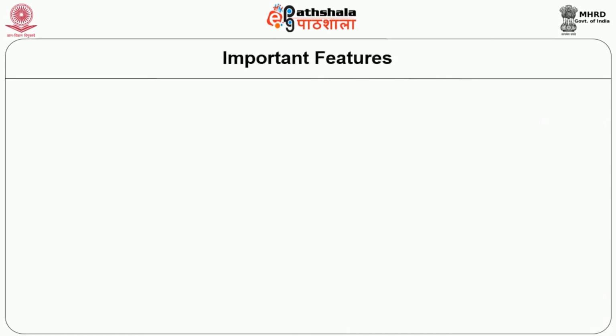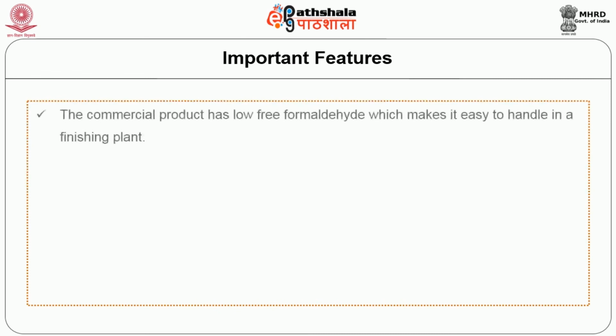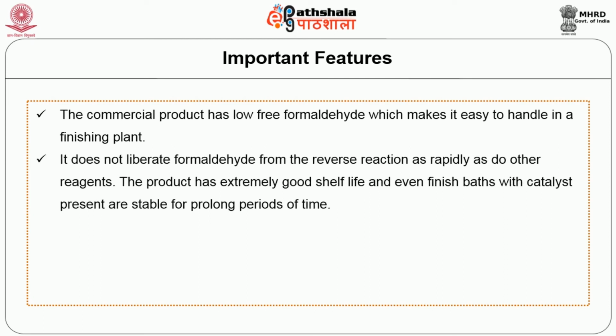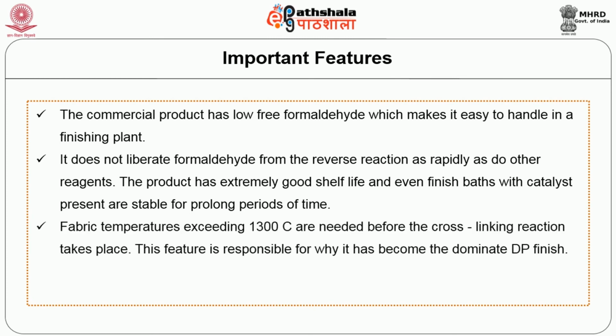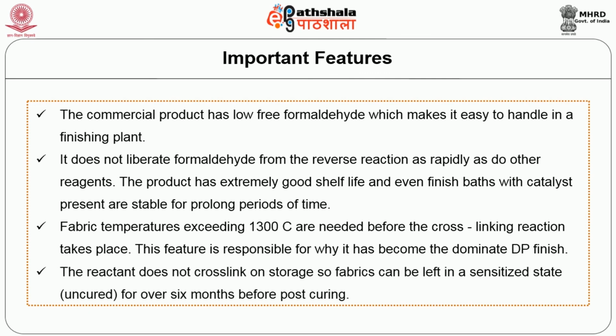The important features of dimethylol dihydroxyethylene urea: the commercial product has low free formaldehyde, which makes it easy to handle in the finishing plant. It does not liberate formaldehyde from the reverse reaction as rapidly as do other reagents. The product has extremely good shelf life and even finish baths with catalyst present are stable for prolonged periods of time. Fabric temperatures exceeding 130 degrees Celsius are needed before the cross-linking reaction takes place. This feature is responsible for why it has become the dominant durable press finish. The reactant does not cross-link and fabric can be left in a sensitized state for over 6 months before post-curing.